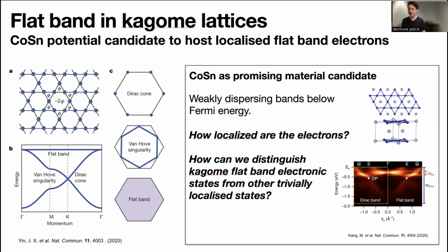Now, the natural question arises: if we can detect these flatbands, we know they exist in nature with perhaps some, it seems, finite small dispersion. How localized are the electrons? And another interesting question, which came to our mind as we were conducting these studies, is how can we actually distinguish such a localized Kagome flatband from trivial localized states? Say, when you conduct an ARPES experiment, you cannot necessarily distinguish between a surface resonance and a Kagome flatband. Both appear dispersionless, but it's quite challenging to make a distinction. It turns out STM measurements are quite suited to make this distinction, as you will see in the following.